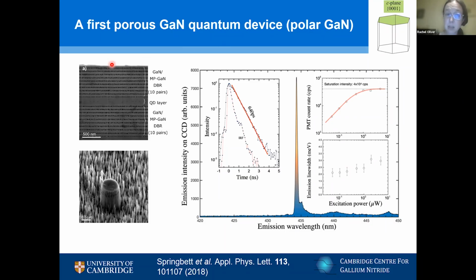It's actually the structure we did the microscopy on that I showed you earlier. Two distributed Bragg reflectors, and a quantum dot layer sandwiched between the two distributed Bragg reflectors. And we then used our microsphere lithography technique to create these little micropillars. Has to be said, it's a pretty ugly micropillar, particularly at this stage in the experimentation. We had a lot left to learn about etching, dry etching here, porous GaN.